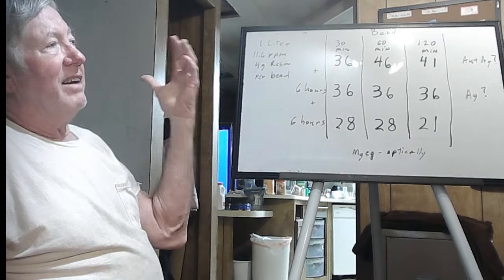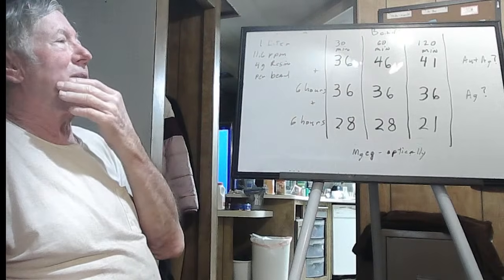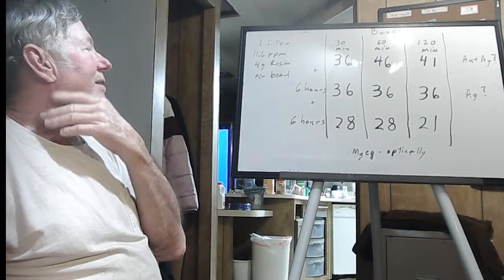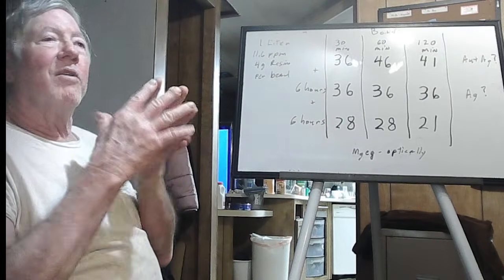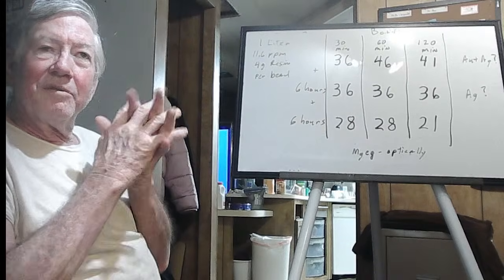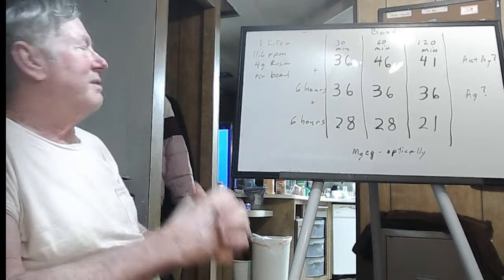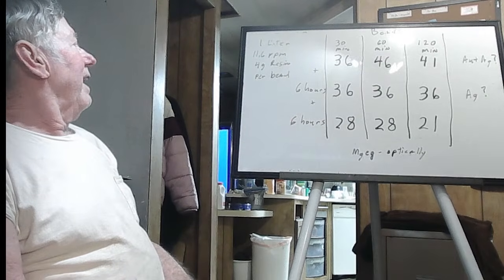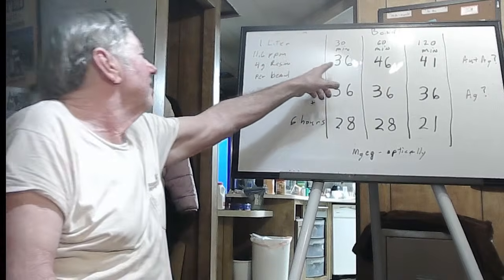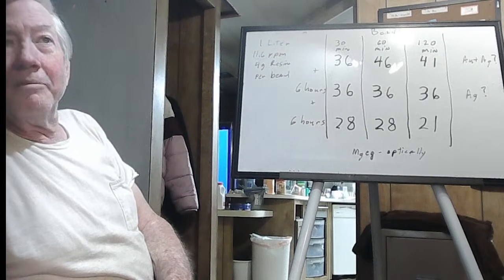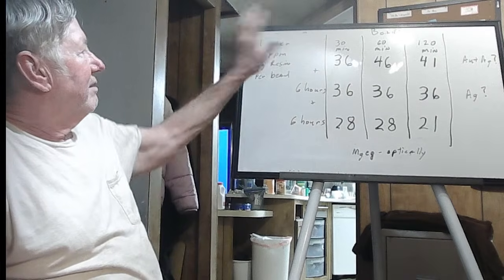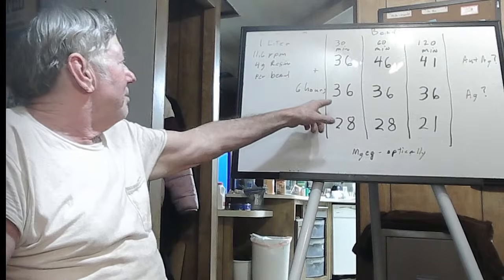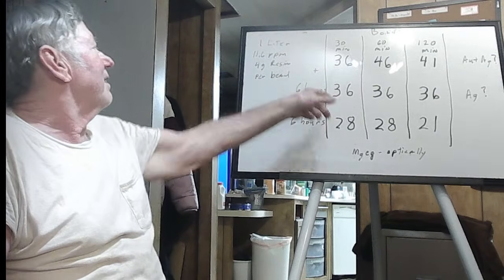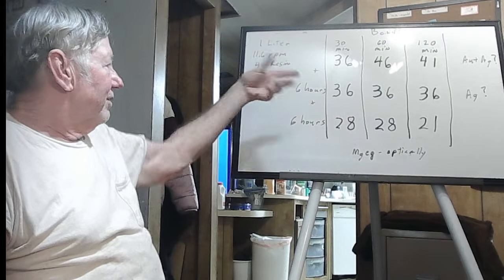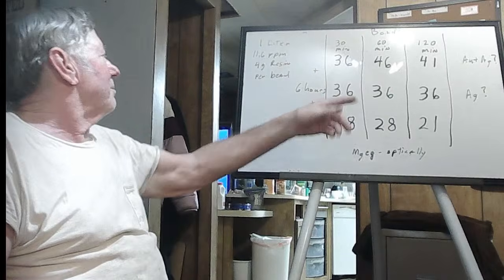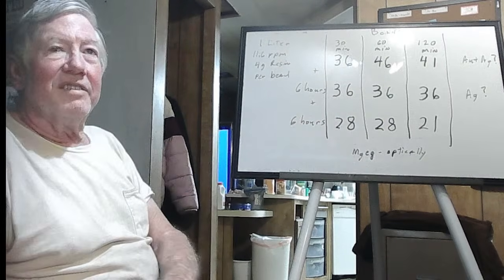Now, I don't have the ability to get solution samples back quick without excessive price. So I thought, what I will do is take that resin and fire assay the resin, which is relatively simple for me to do. So I took 1 sample, bottle rolled a batch of resin in it for 30 minutes, took the resin out, fire assayed it. Then I put another batch of resin in there, another 4 grams, ran it for 6 hours, took it out, fire assayed the resin, and put in another batch of 4 grams for another 6 hours.